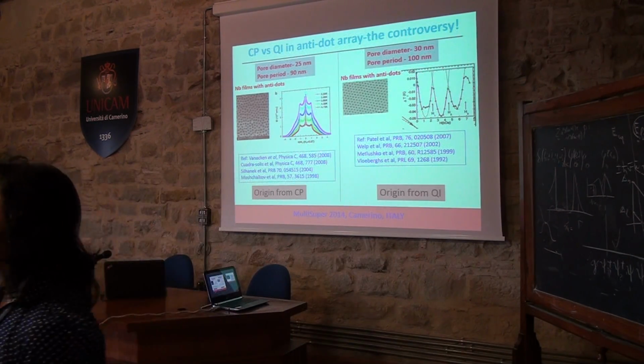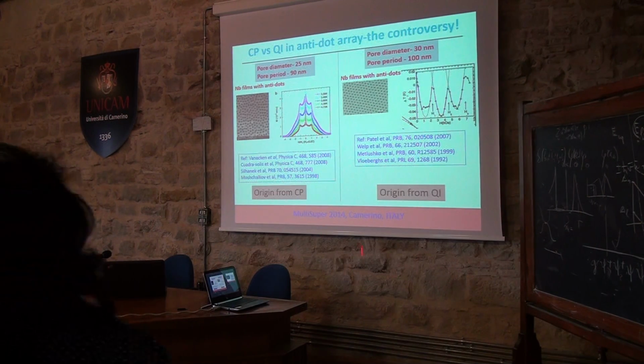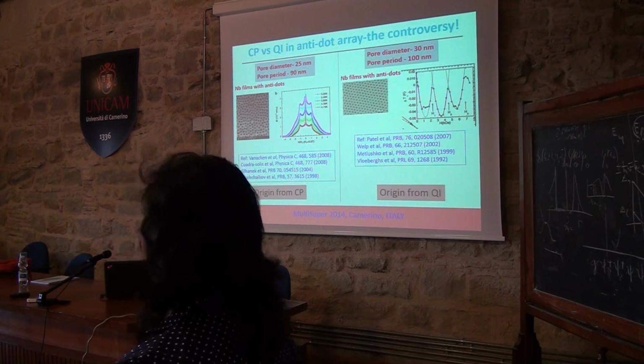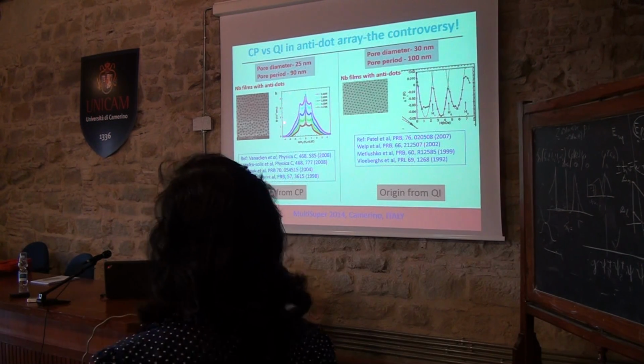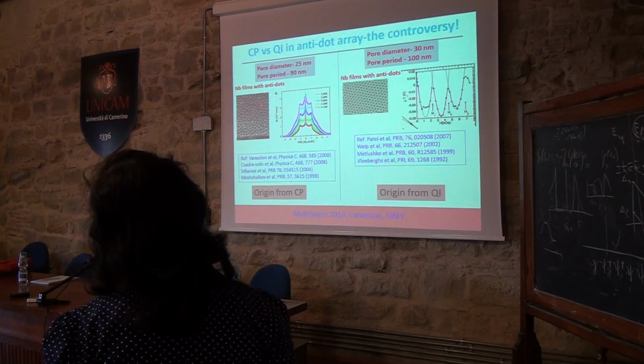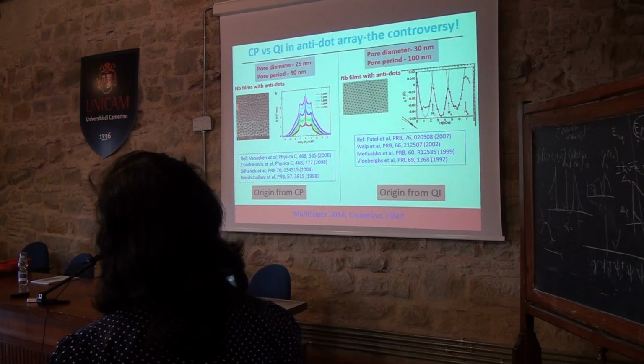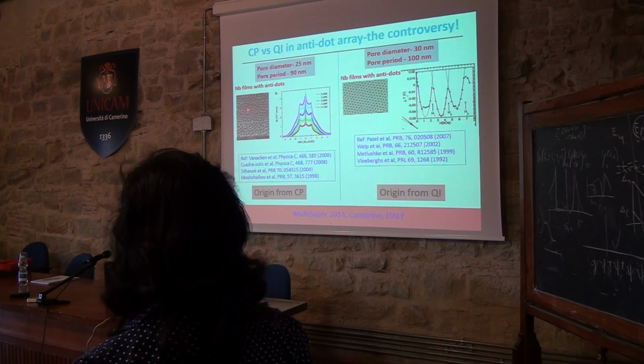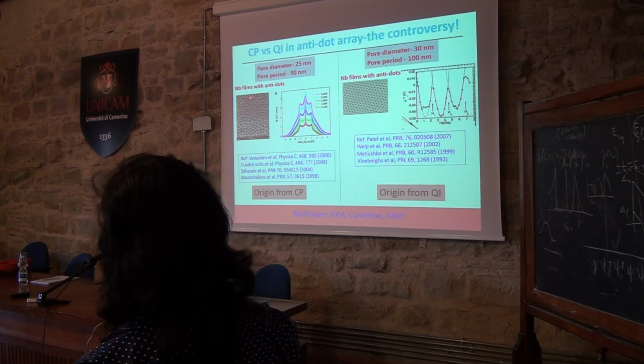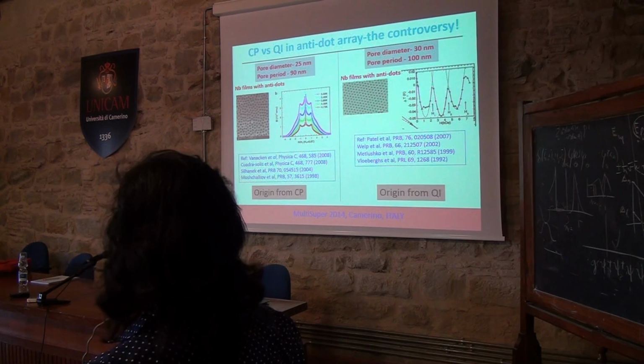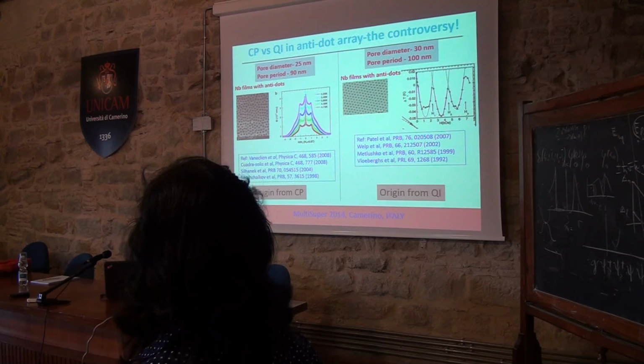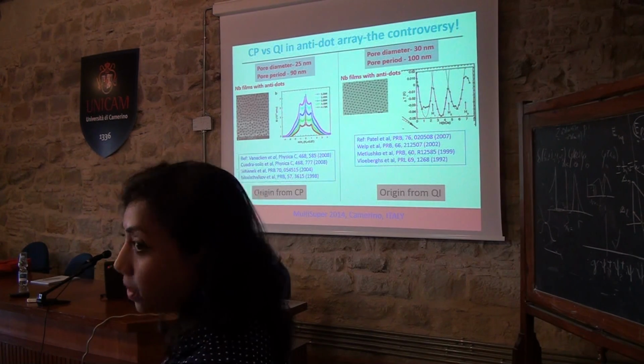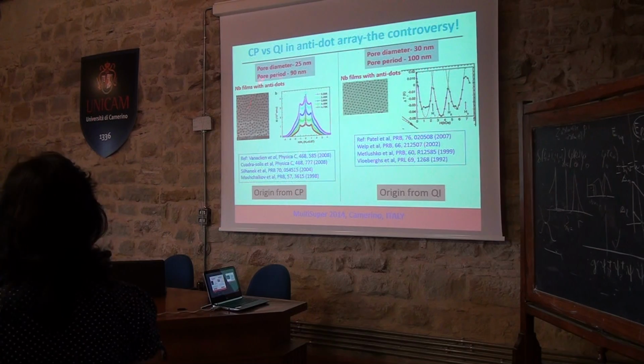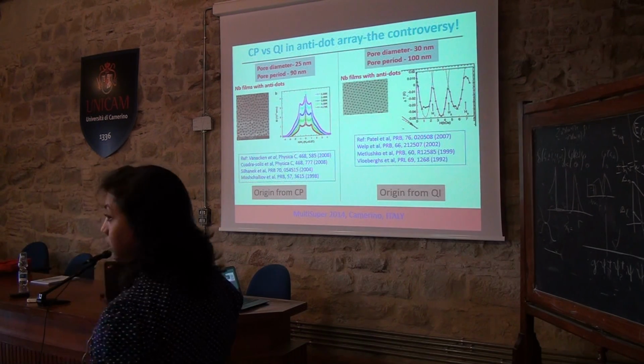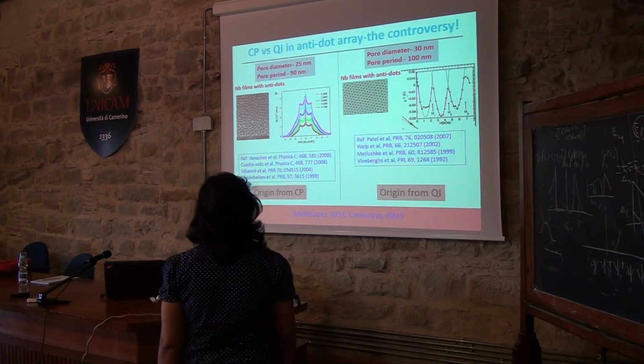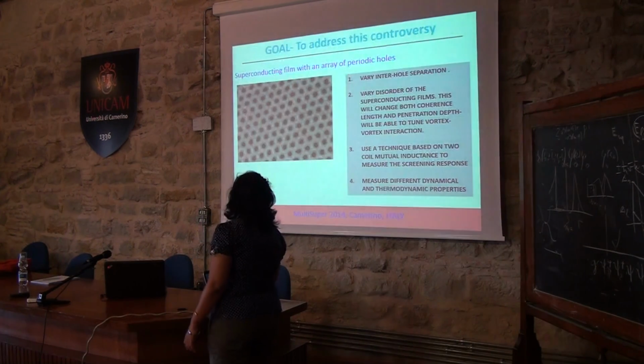So the motivation of taking up this project comes from the literature. As I said, people have done these studies in very similar kinds of systems, like these samples of superconducting niobium which had these antidots, and the size of the antidots was about 25 nanometer and 30 nanometer in this case, and the explanations were completely different. In these they were explained through commensurate pinning, while in this they were explained by quantum interference effects. So they were varied opinions.